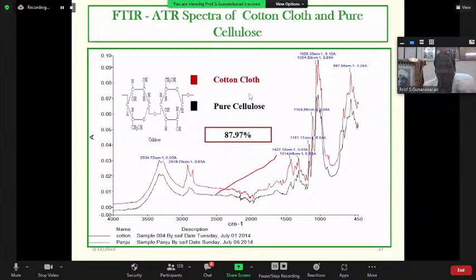Suppose you do not have the ATR technique in your FTIR spectrophotometer, it is not possible to record the IR spectrum of cotton, because we can't prepare the KBr pellet; with a fiber, cellulose, we could not get a fine powder. So it's not possible to record the IR spectrum of cotton cloth using a conventional FTIR spectrophotometer. It is possible only with the ATR technique. Putting a piece of cotton on the diamond crystal, by giving suitable pressure, we can get the spectrum within 32 seconds.